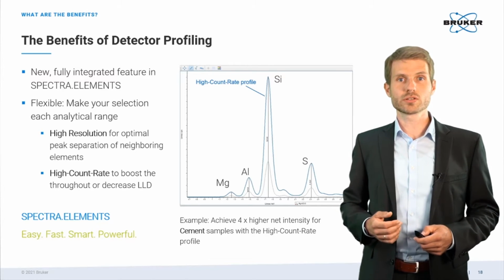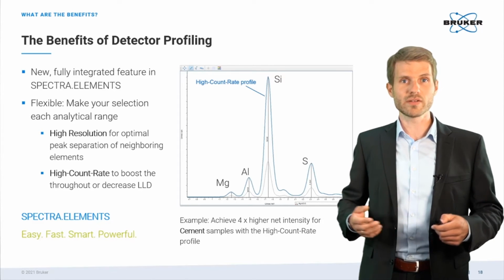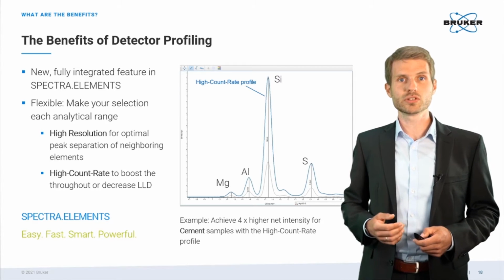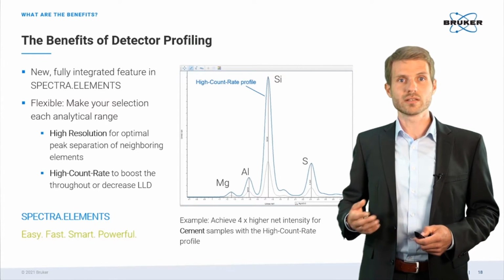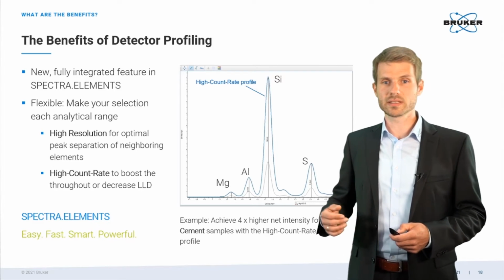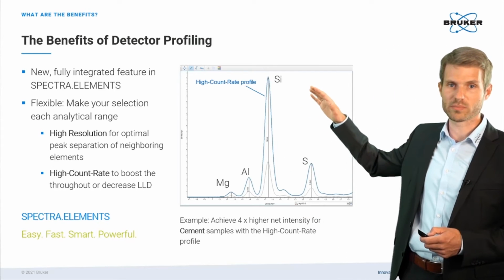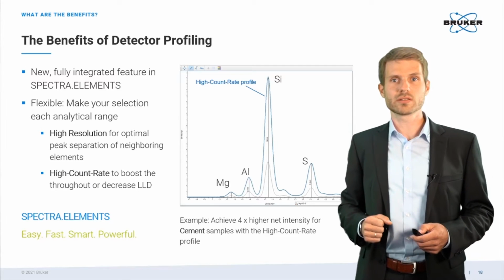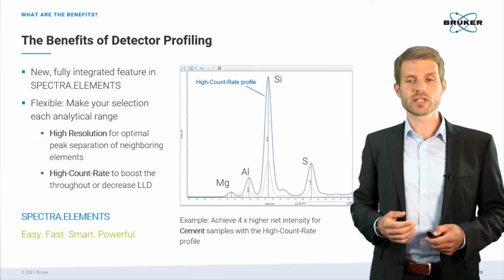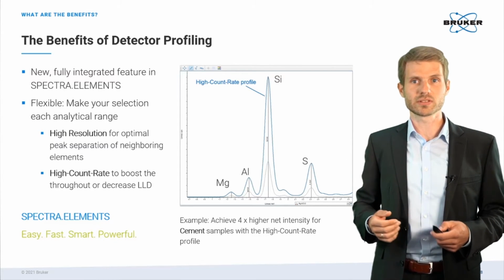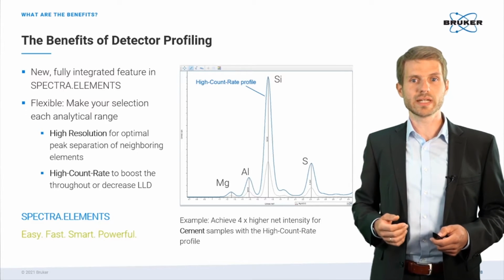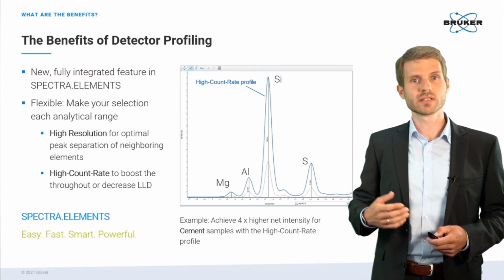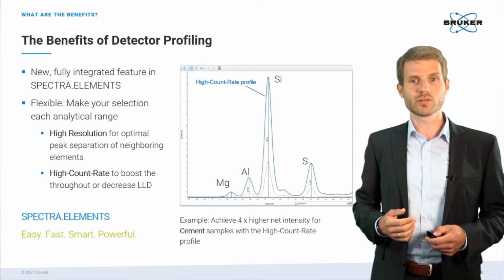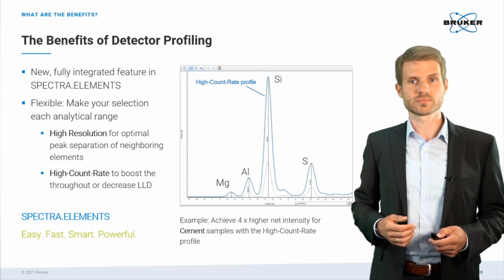Or if you want to achieve lower limits of detection for heavier elements, you might want to boost the count rate to get lower limits of detection. As you can see here in this example for a cement measurement, with the high count rate, you can achieve up to 400% higher intensity for a cement sample. And this really pays back and can be used, for instance, to reduce the counting time and therefore increase the throughput substantially.